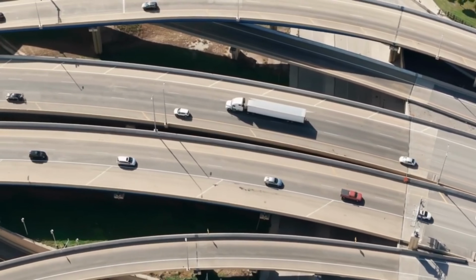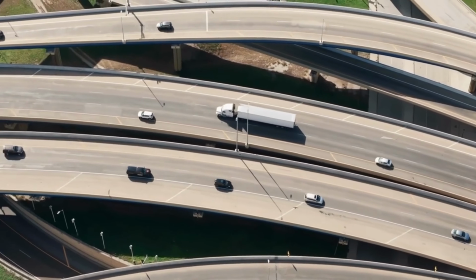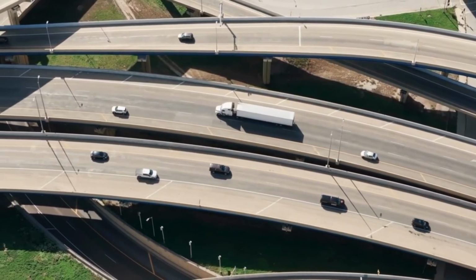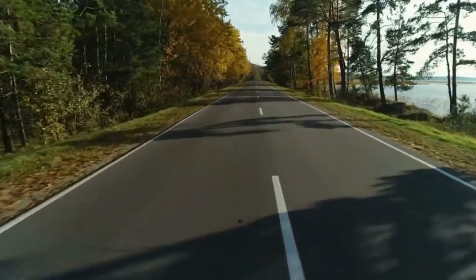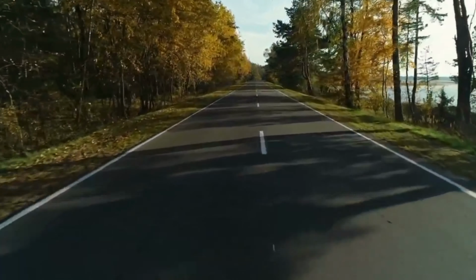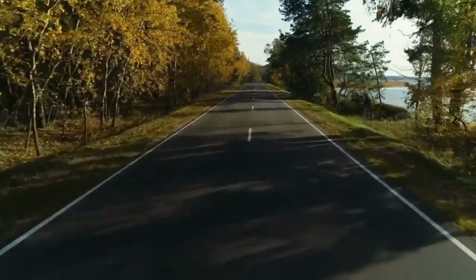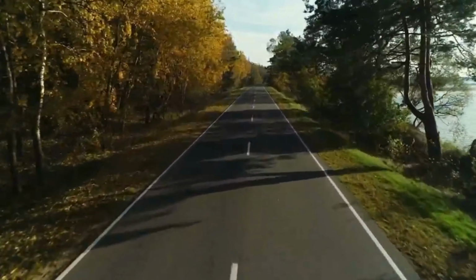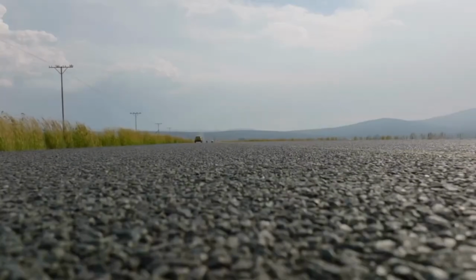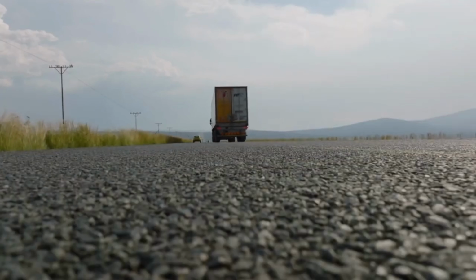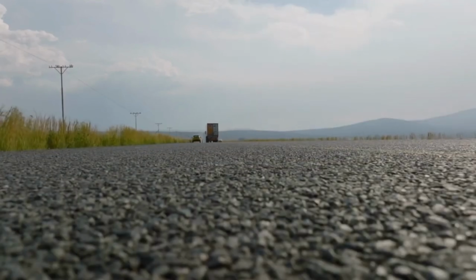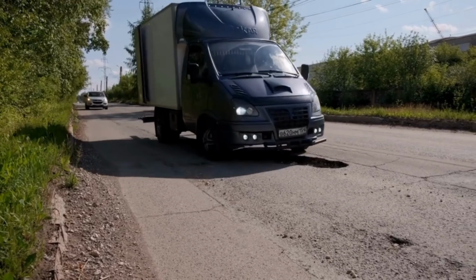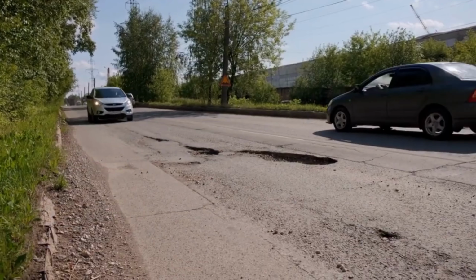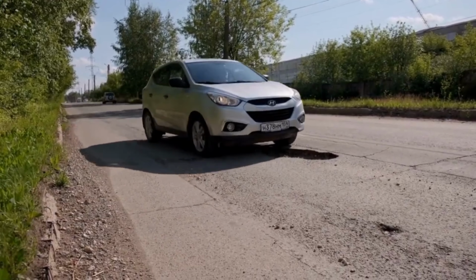Highways often consist of multiple layers. The base course, thick and strong, provides structural support. The binder course sits above it, adding durability. The surface course, the top layer, uses smaller aggregates for a smooth, quiet ride and excellent skid resistance. Each layer is paved and compacted separately with tack coat, a thin layer of sprayed asphalt emulsion, applied between layers to ensure bonding. Without proper bonding, layers can slide or delaminate under traffic, causing potholes or rutting.